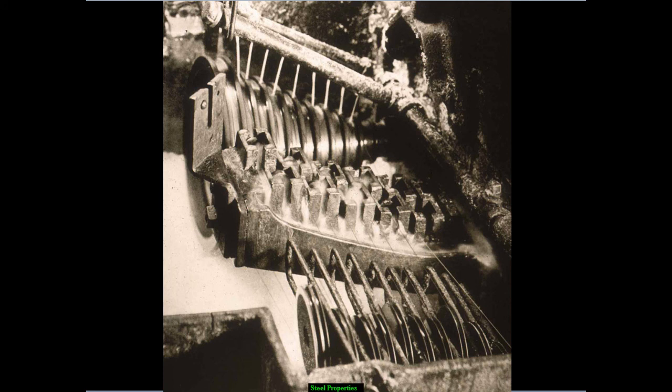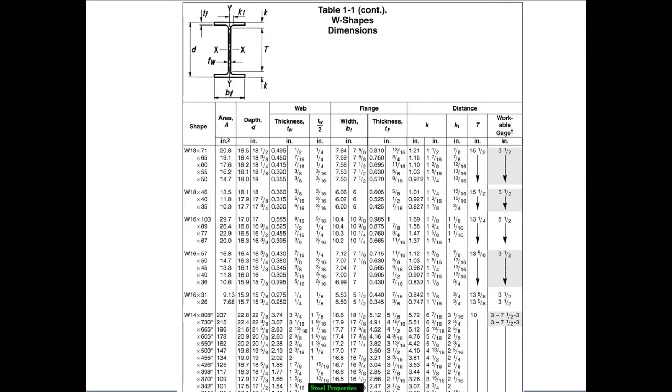So I'm going to give you some quick numbers, by the way. Let's go back up here and we'll talk about wide flanges. I think I mentioned before that they used to come a lot in 36 KSI. 36 is largely being phased out except for the jumbo sections, and most of them have a yield stress of 50 kips per square inch. And that's a number I would like for you to remember. You can get it up to 65, but our most common wide flanges and angles and channels are 50 kips per square inch for the yield stress.